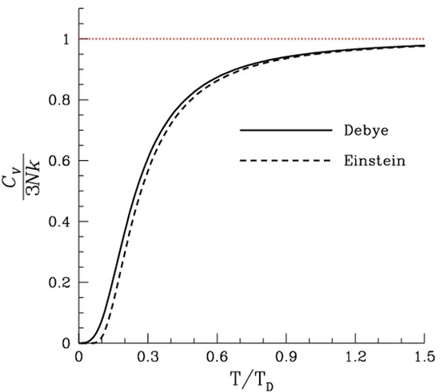The molar volume of solid elements is very roughly constant, and even more reliably, so also is the molar heat capacity for most solid substances. These two factors determine the volumetric heat capacity, which as a bulk property may be strikingly consistent. For example, the element uranium is a metal which has a density almost 36 times that of the metal lithium, but uranium's specific heat capacity on a volumetric basis, i.e. per given volume of metal, is only 18% larger than lithium's.